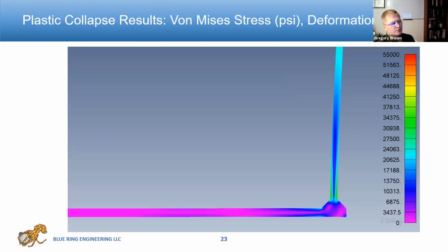So here's an example of the plastic collapse analysis that was done. As it turns out, the structure remained stable under the loads, even with the factors of safety that are required. What you see is the tank shell here kind of bending outward, and you see high stresses. In this picture, this is what's called von Mises stress or equivalent stress, occurring right at that floor to shell weld. Usually this is the key location. You get significant bending stresses at this location, especially for tank settlement. This is usually the case that will actually govern the assessment.